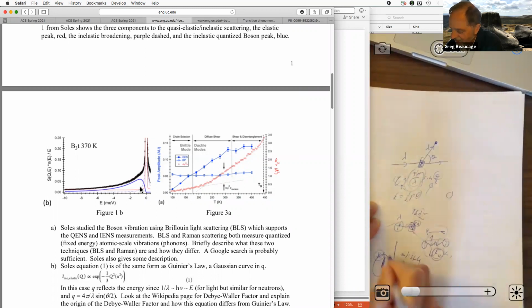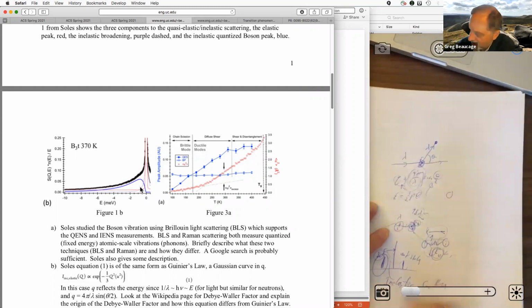And then the distance in energy between the peak that came in and what came out is the energy of that absorption. So that's inelastic spectroscopy or scattering. And depending on what that thing is that transferred the energy, that's the difference between Raman and Brillouin light scattering. If it's a bond the way I did it here, then that's Raman. So if you're looking at bond vibrations, then that's Raman scattering.